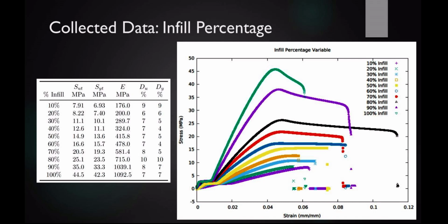This is likely because when you have less material on the inside, the voids don't act so much as stress concentrators as they do allowing the material to actually move slightly and deform around that load. So as you put it under load, all those little holes, which are normally square, become little diamonds, and then it's able to continue sustaining that load. With 100%, you just don't have that space, so they act as voids. They create stress concentrations just like any other void, and then it fails earlier.